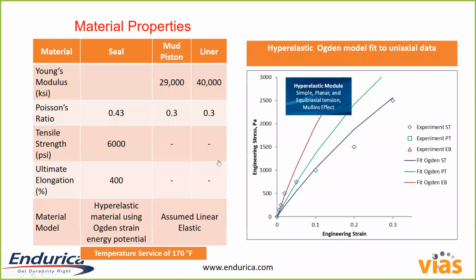So in our analysis, we've used these material properties. There's a liner and the piston itself that are metallic things. Those are linear elastic. The seal is, of course, the interesting part. We've used an Ogden strain energy potential here, and we've plotted out the stress strain curves. The data points are shown. For this problem, we actually had limited experimental data, but we've done our best to fit a